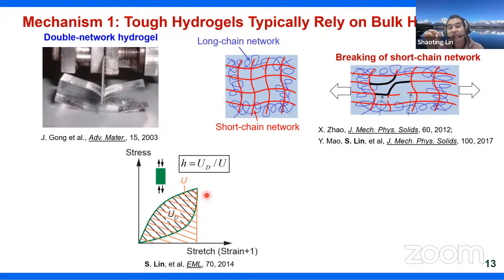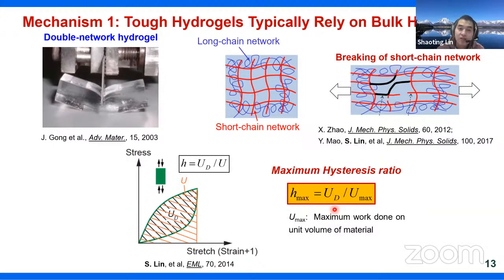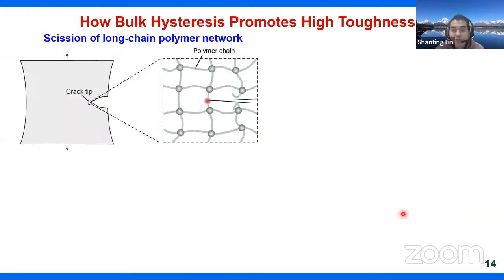So this is a stretch-dependent variable. The higher the stretch, the higher the hysteresis ratio. We denote H max as the maximum hysteresis of the material. So the message I would like to deliver in this slide is that breaking of the short chain network gives a high maximum hysteresis ratio. Then the follow-up question is how the presence of the bulk hysteresis promotes high toughness enhancement. So here is what happens at the molecular level. For double network hydrogel, first and foremost, it also involves the scission of a layer of the long chain polymer network, which contributes to this gamma naught, as I just explained. But this is still a relatively low number.